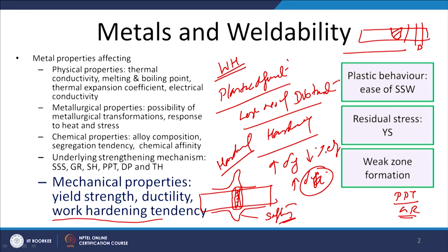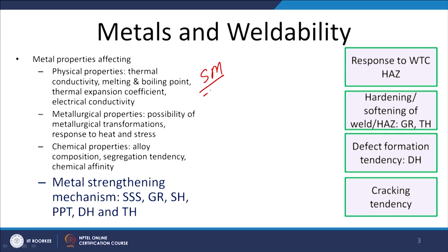But if softening is taking place, wherever the soft zone is being formed, either in the weld metal or in the heat affected zone, the failure will be occurring from the minimum hardness zone. So, that is why we can see the role of the mechanical properties of the weld metal with regard to weldability. Now, we will see how the strengthening mechanism used for designing a given metal system will be affecting the ease of welding.